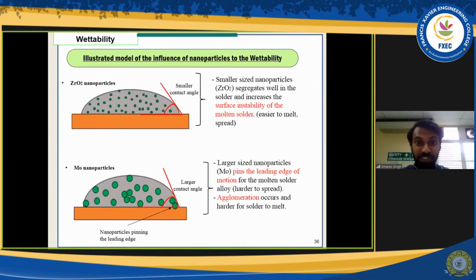I have illustrated a model of my own. This is my own model that I've illustrated. What happens when we have the zirconia and molybdenum? In my particular study, the zirconia nanoparticles are much smaller compared to the molybdenum nanoparticles. Smaller nanoparticles have better segregation properties, so they are more evenly and properly distributed. So a smaller contact angle is produced. Whereas for the larger molybdenum, they tend to have van der Waals force that attracts the nanoparticles together. So the process of reducing the contact angle is not as efficient as with zirconia. So that is the reason for this.